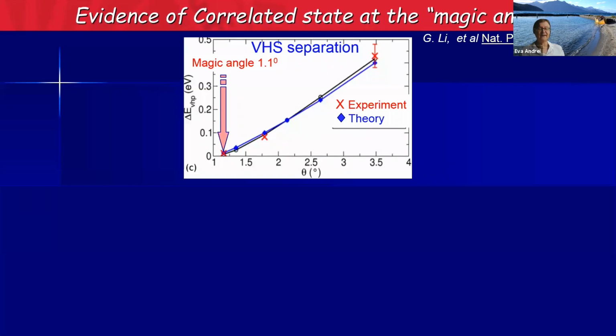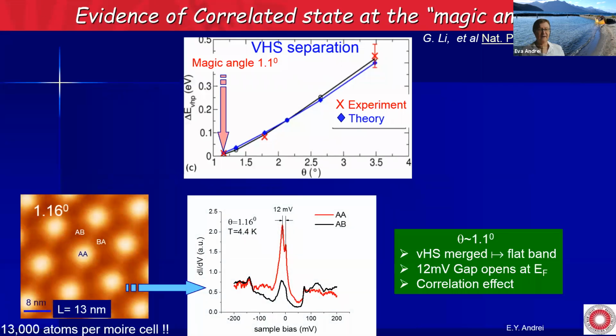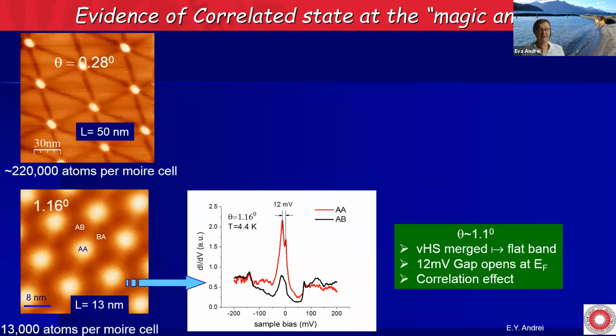But what's interesting here is that there is a point before you reach 0 degrees where the separation goes to 0. And this is what later was called the magic angle. And this is the data at the magic angle. So this is 1.16 degrees. You see the Van Hove singularities have merged. Here at the Fermi energy, which is always the 0 in STM, you see a small gap, which we interpreted as a correlation effect at the time, as a charge density wave. Of course, you can go beyond the magic angle, 1.1 degree, to a much smaller angle.